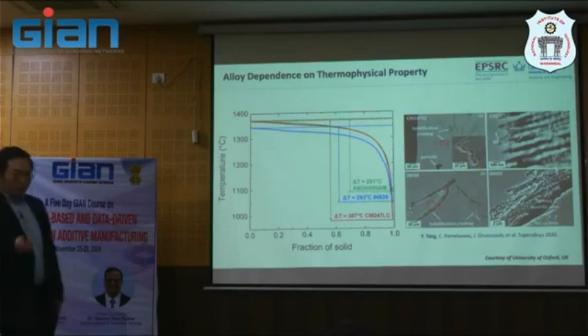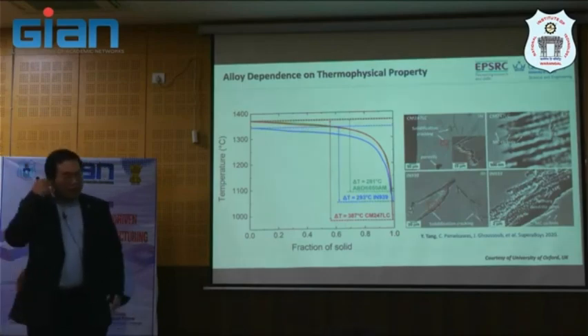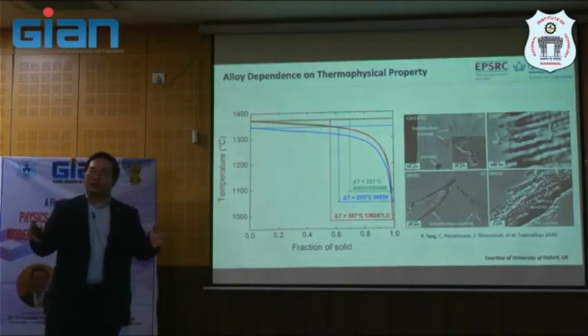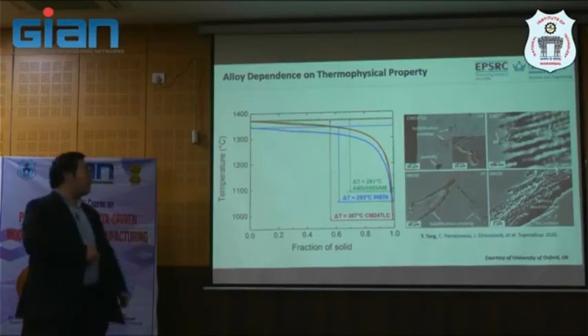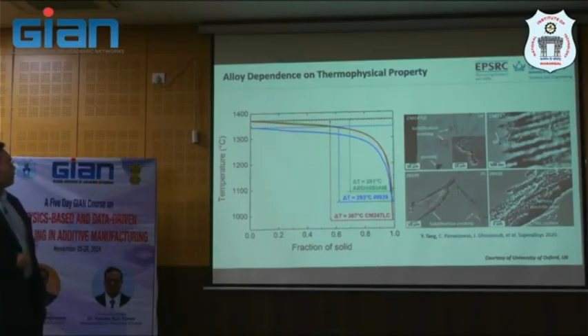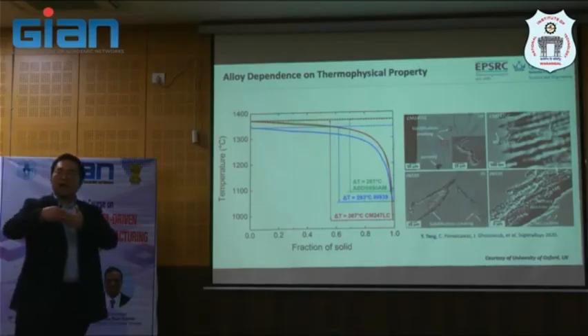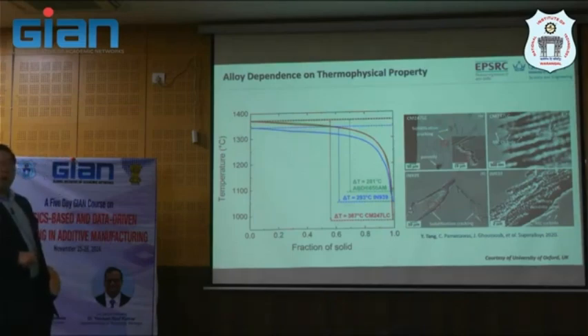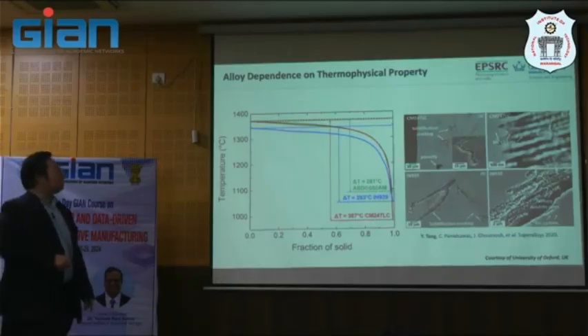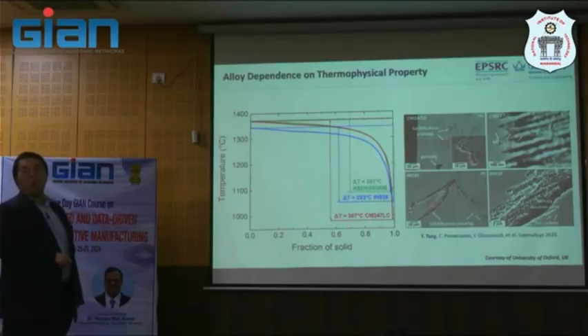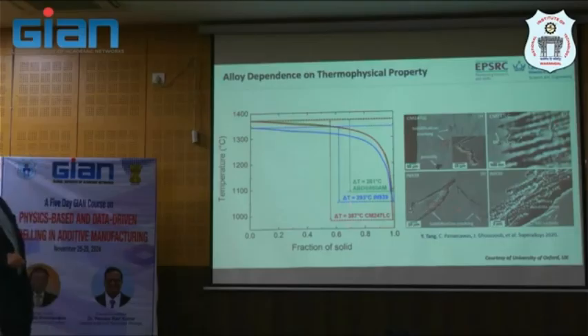try to predict. Because as I mentioned briefly previously, if you have a larger freezing range, you are prone to have more cracking than with a shorter freezing range. And this is confirmed by the model: the freezing range in CM247 is almost 400 degrees centigrade. There is a very large temperature gap in which a crack can form, compared with some new alloy designs, which are reduced by, I think, about 35% less freezing range than the very non-weldable or very problematic alloy here. So this shows that this thermophysical property contributes to the cracking that you see here as well.